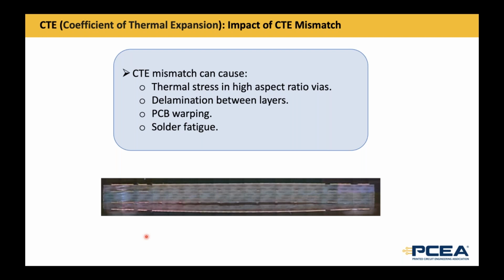You can also, especially with the boards that have a higher aspect ratio, copper coating along the via walls tend to be thinner, making the center more vulnerable to thermal stress and cause cracking. And another thing to think about is chip package. I know today we're talking more about PCBs, but the chip package usually has a lower CTE, a lot lower than the PCB. So when the board is heated, the package will expand less than the board and can result in a bad solder joint connection. Obviously, the difference in CTE will matter more when the chip package sizes are larger.